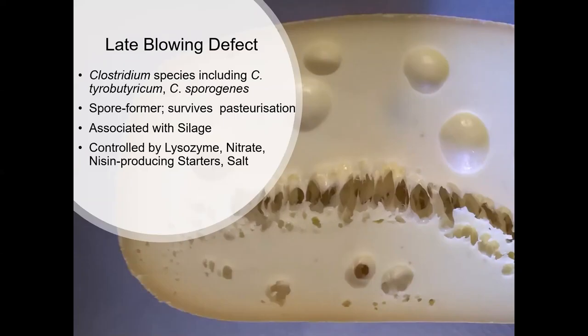It can also be inhibited by effective salting. Undersalted cheeses will be more prone to late blowing defect than the correctly salted cheeses. So these are things that we can do to try and prevent it. But there's one other step that we can take to try and reduce its likelihood as well. If we absolutely have to feed silage, we would have to accept that there are going to be some spores present and they'll make it into the feces of the milking animal. And if there's any fecal contamination of the milk, that is going to introduce the spores back into the milk. So significant attempts to reduce fecal contamination during milking can actually have a positive impact on reducing the incidence of late blowing defect. Taken alongside a reduction in silage use wherever possible, and other controls such as correct salt levels or the use of inhibitory substances such as lysozyme, we should be able to reduce the likelihood of this happening.